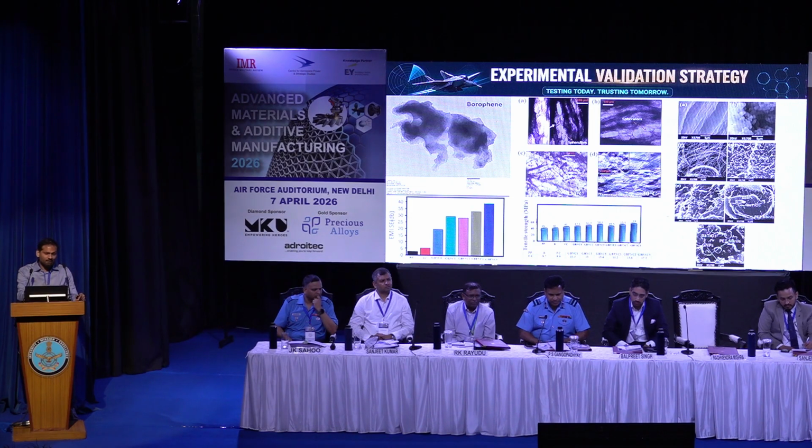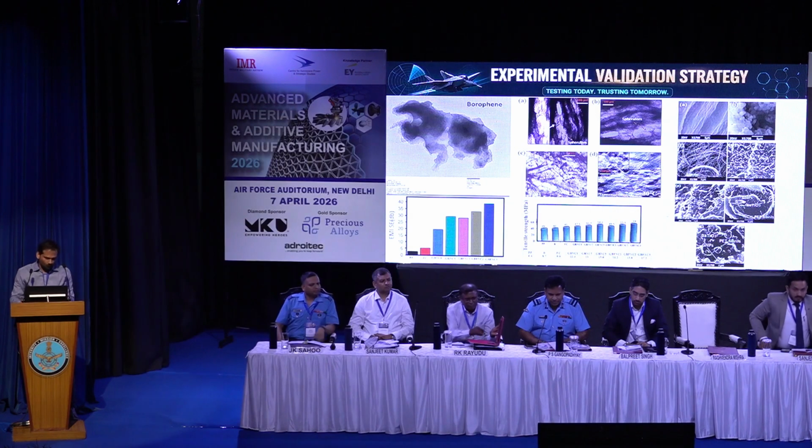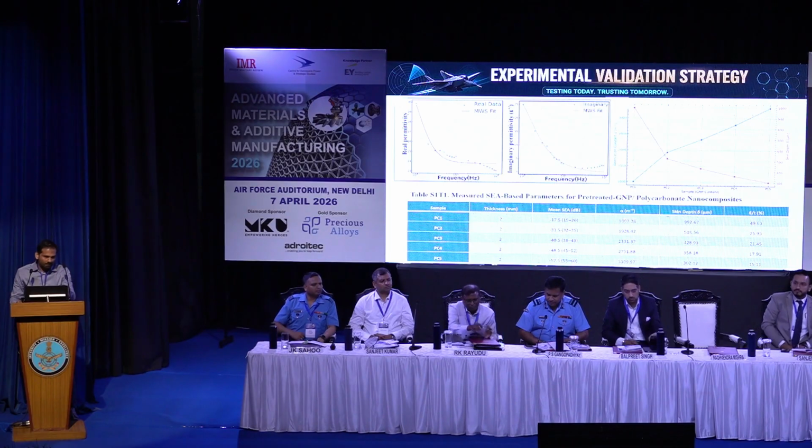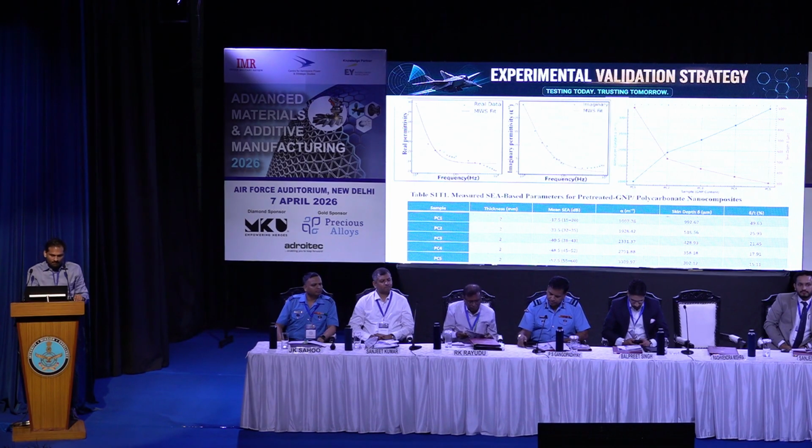Then here I developed some materials, because here you can see the spherical thing. A sticky, fiber-like structure I developed with the help of the nanomaterials. Here are fibers and also selective localization of nanomaterials in the system. And you can see I improved EMI shielding. And here are real permittivity and other properties of the nanomaterials used for EMI shielding and stealth technology. Here the MWS is the Maxwell-Wagner-Sillars effect, mostly important for stealth and polarization effect.